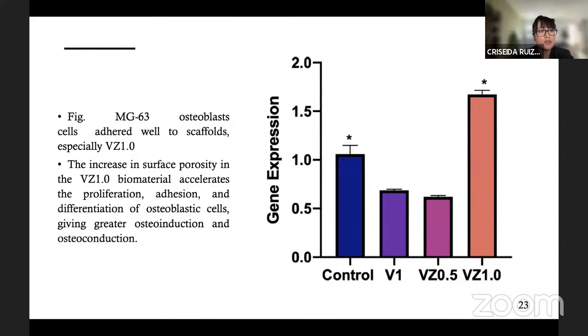And then it continues with the in vitro part. The scaffolds were evaluated in vitro with MG63 osteoblasts. The cell adhesion and the effect of the porosity of the scaffold are analyzed, and the sample with the higher zirconia content accelerates the proliferation, adhesion, and differentiation of the osteoblasts, resulting in better osteoconduction and osteoinduction.